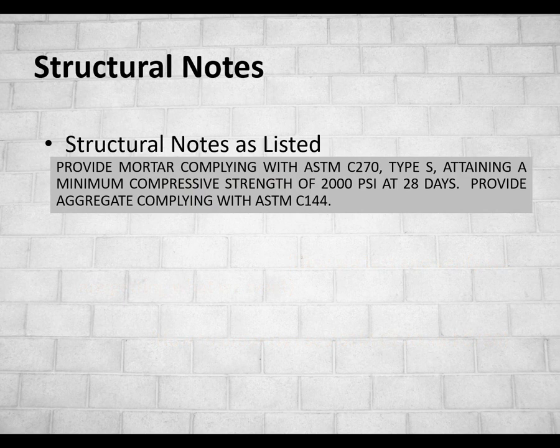Provide mortar complying with C270 type S attaining a minimum compressive strength of 2,000 PSI, 28 days. What? Where did 2,000 come from? It's not even associated with any strength of mortar. We have 2,500, 1,800, 750, and 375. It doesn't even come into play. Probably the masonry design strength was 2,000 PSI. Oh, I'll make the mortar the same thing. Doesn't quite work like that, unfortunately.